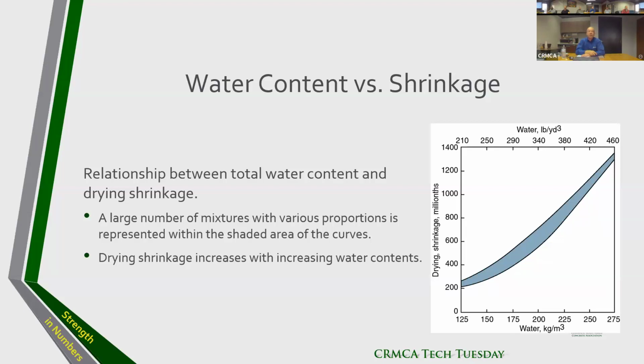Water content versus shrinkage. In this case, we see at the top from 210 to 460 pounds of water per yard, and the drying shrinkage, how it increases. That's a pretty old graph, also from the PCA booklet. A large number of different mixtures, different proportions were done, and they show the shrinkage of the concrete. And what we see in the end is that the more water we have in our concrete, the higher the shrinkage of the concrete. So again, don't add any more water at the construction site if you don't have to, or the shrinkage might increase.